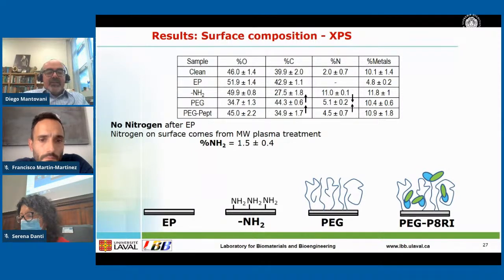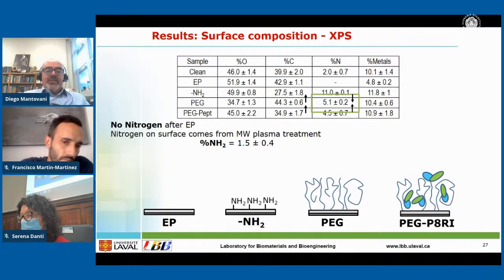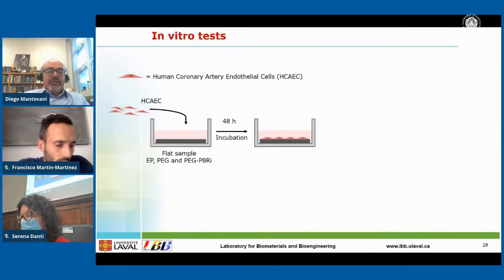This is an interesting table because you can see the evolution of what you bring to the surface, and you can notice that oxygen and carbon presence increase during the PEG grafting and the peptide grafting. What is important is to see that basically 5% of nitrogen was the targeted approach.